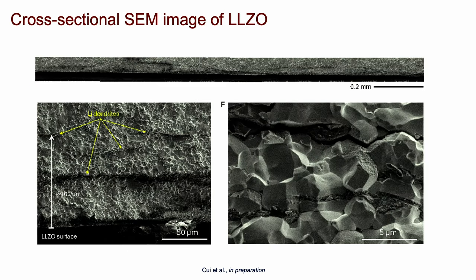If we now take that sample and break it in half and look at the side, we see that the cracks that are forming are parallel with the surface. They're no longer going in the harmful direction, from one electrode to the other. It looks like cracks are still forming. It would be against the laws of physics if cracks just weren't forming at all. But they're now going in this direction that's not harmful to the performance. So that's kind of good. We can redirect this process.